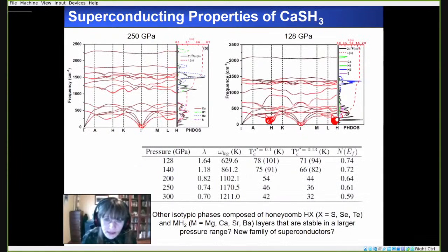We then estimated the superconducting properties of the CaSH3 phase. The highest Tc was about 100 Kelvin at 128 gigapascals, which is still quite high, not room temperature, of course. But what is exciting about our work is that it proposes a new family of superconducting species that could be built by, for example, replacing the alkaline earth metal by other alkaline earth metals such as magnesium, strontium, and barium, and also the sulfur by other species such as selenium and tellurium. And we have done preliminary calculations showing that indeed these types of phases could be dynamically stable under pressure.